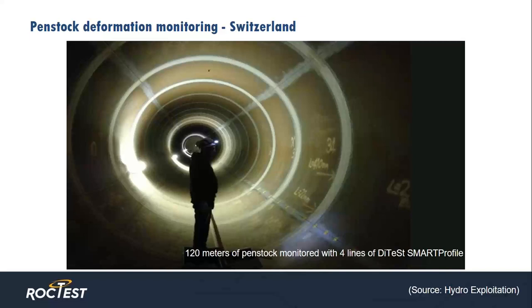And they suspect that the culprit here was an earth flow occurring in the adjacent soil, progressing at a geologically high rate of speed of about a half millimeter a year. They also suspect that another culprit for the welds failing was some poor welding control during the construction phase. About 120 meters of the penstock were monitored with four runs of Ditest smart profile. And as you can see here, they were glued with epoxy to the penstock walls.